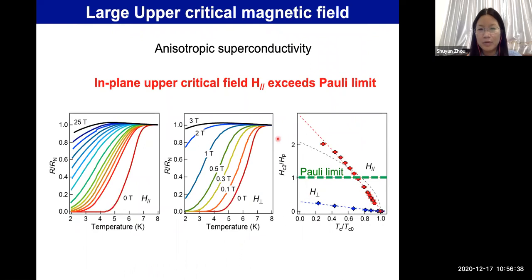To further confirm the 2D superconductivity, we also perform resistivity measurements under different in-plane and out-of-plane magnetic fields. We can see that the superconductivity is not so sensitive to the in-plane magnetic field. However, it is very sensitive to the out-of-plane magnetic field. And if we plot the upper critical field as a function of temperature, we can see that this in-plane upper critical field actually exceeds the Pauli limit.